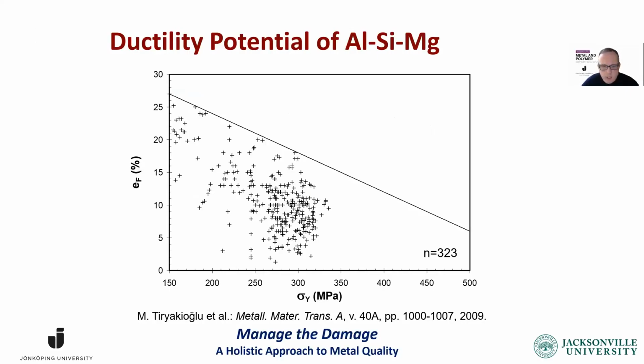So about 10 years ago, I looked at the premium casting and aerospace casting literature. I put in all the data that I could find on several alloys. This is for aluminum, silicon, magnesium alloys. We have about 323 data points here. And what became obvious is that the maximum points form a trend when you plot yield stress on the x-axis and elongation on the y-axis. That seems to be the intrinsic ductility-strength relationship compromise, as we learned in the textbooks. So we call that the ductility potential of the alloy. You will see that, for example, at 200 megapascals, we are capable of getting about 24% elongation from the casting. Again, these are actual numbers. These are not estimates or theoretical values. These are actual numbers.